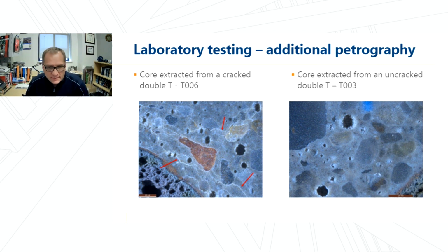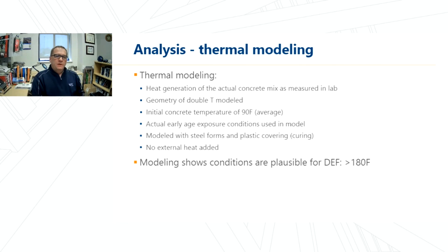So you may be asking why, and we'll get to that later. The next part of the investigation process was actually doing some thermal modeling. We wanted to know if we had conditions at early ages of the concrete that would be conducive to the formation of DEF. So we modeled the double T's using the geometry, using the heat signature of the mix, using the information we gathered from the supplier related to the concrete temperature at the time of placement and the ambient conditions during placement and shortly thereafter.